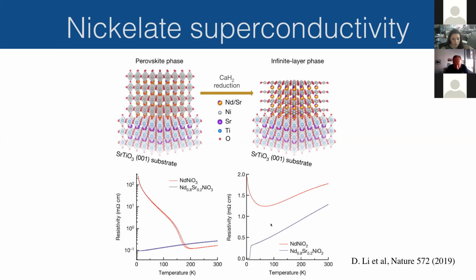So here is the summary of the transport properties of perovskite neodymium nickelate. Here it is, it has its metal insulator transition as it should. When you dope the perovskite phase, it's a metal. This is doped with strontium. Then the infinite layer, neodymium nickel O2, is sort of conducting, but it has an upturn at around 50 Kelvin. Then finally, when you dope neodymium nickel O2 with 20% of strontium, that is when you get the superconducting transition, and this is happening at around 10 Kelvin.